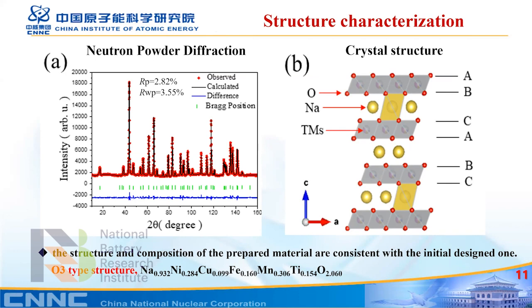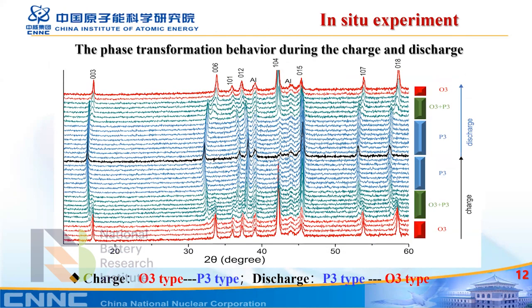That so-called in situ XRD measurement will investigate the structure change during the charge and discharge process. The result is shown here. During the charge process, the 003 peak, I mean this one, you can see from the figure, shifts to a low angle, indicating a solid solution reaction. Then its peak disappears, but a new peak corresponding to prismatic P3, the so-called P3 phase, appears. We can see the phase transition, and upon discharge, the structure changes back again. So we can see the process is highly reversible. This means the material is stable during the charge and discharge.